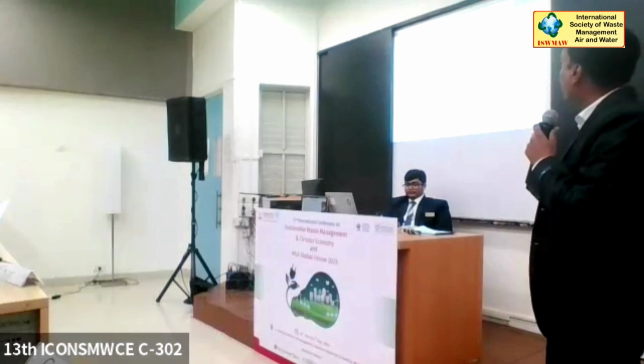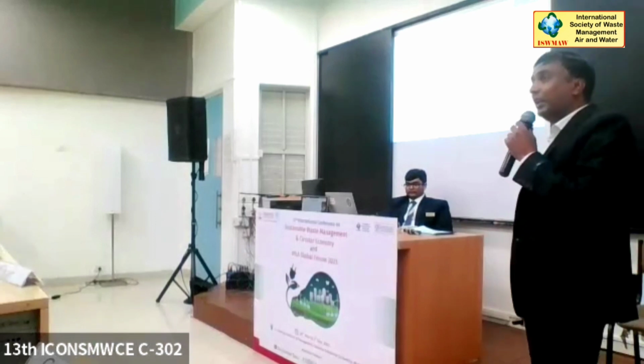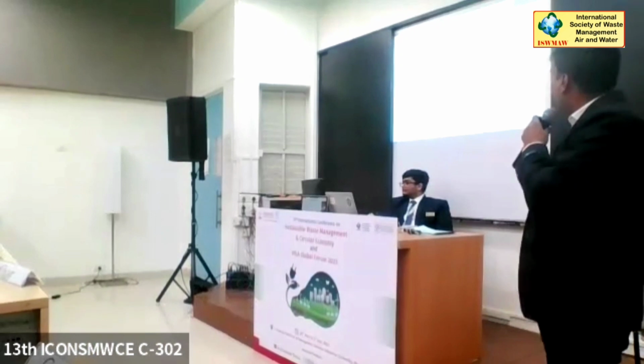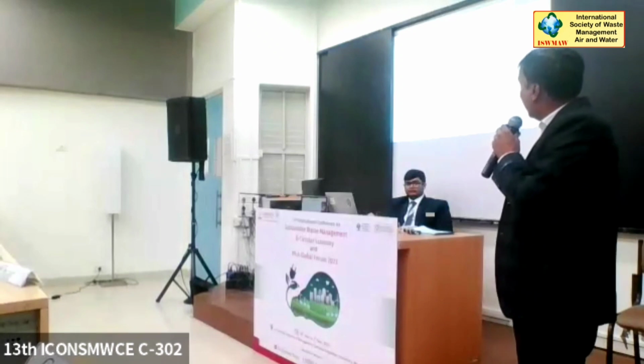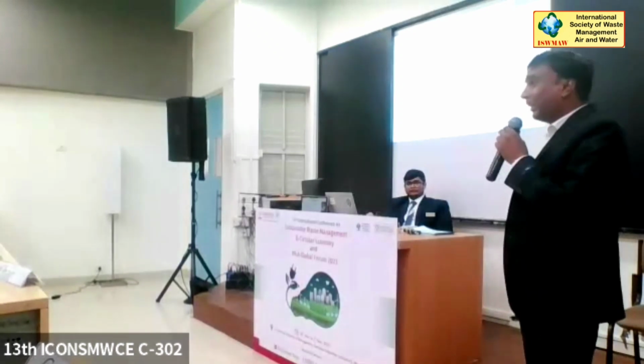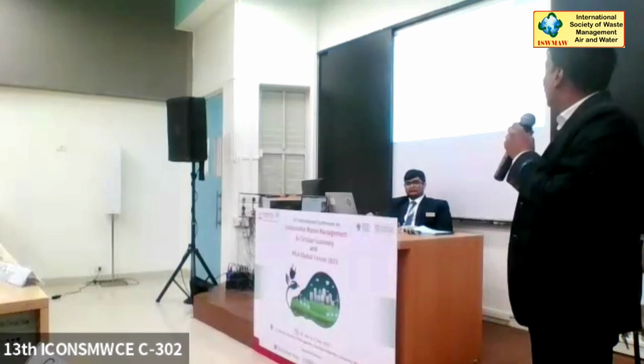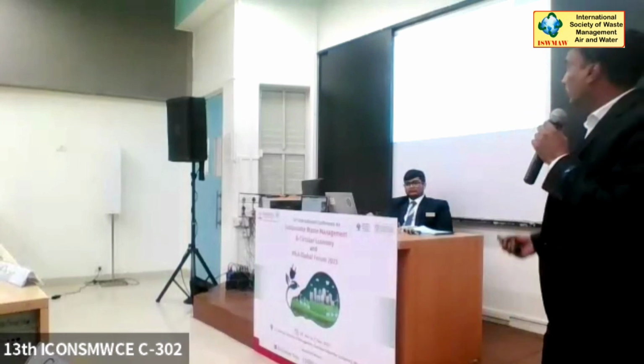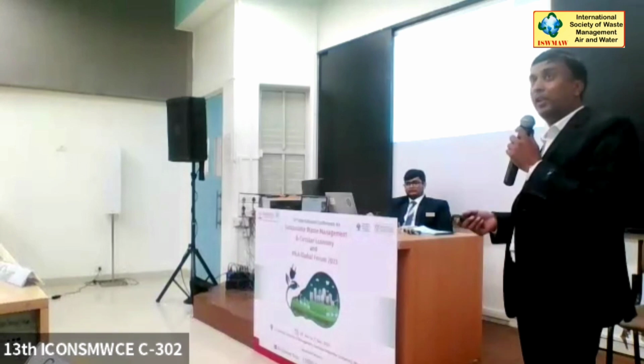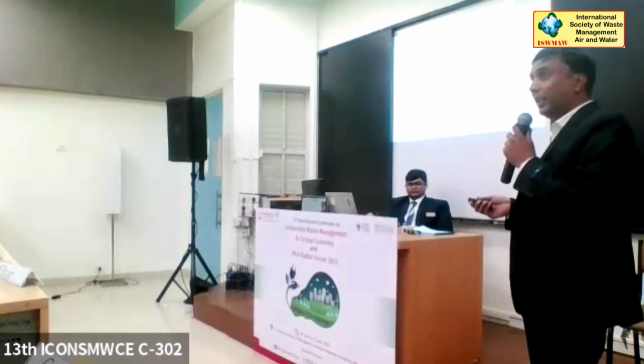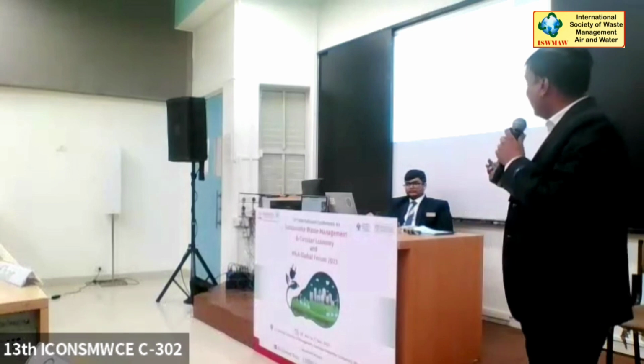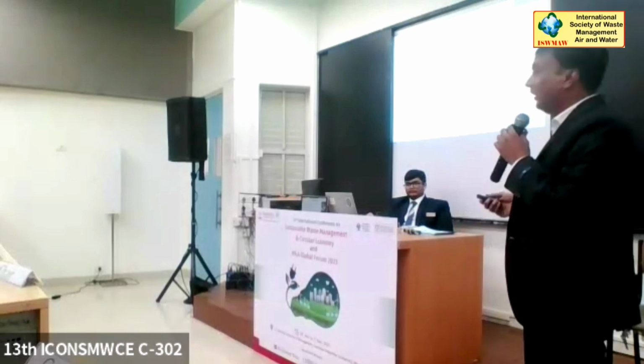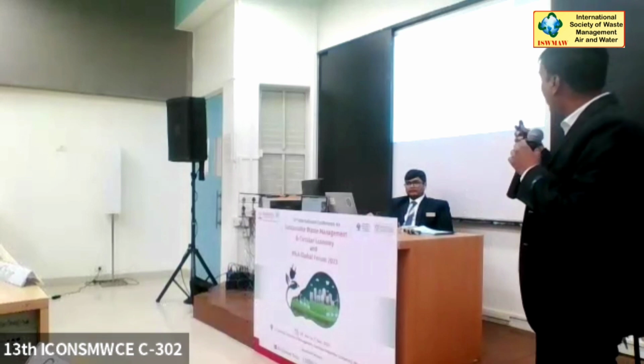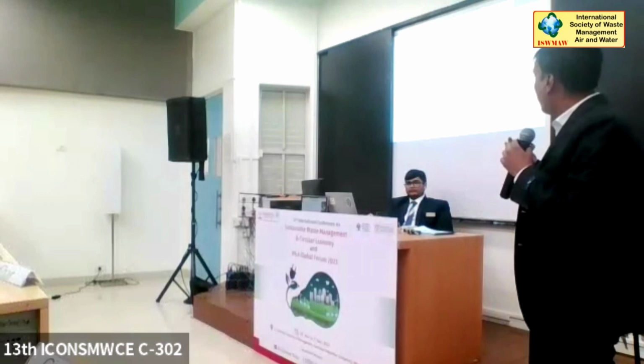Now talking about raw material, we are widely using wet fly ash and slag as a substitute for natural minerals for clinker production. Earlier, we used China clay in place of wet fly ash, and slag we are using in place of red ochre. So both natural minerals we have replaced, and now we are using wet fly ash and slag in raw mix. So total, if we see, 2,99,348 metric tons we have used total raw materials during 2018 to September 2023.